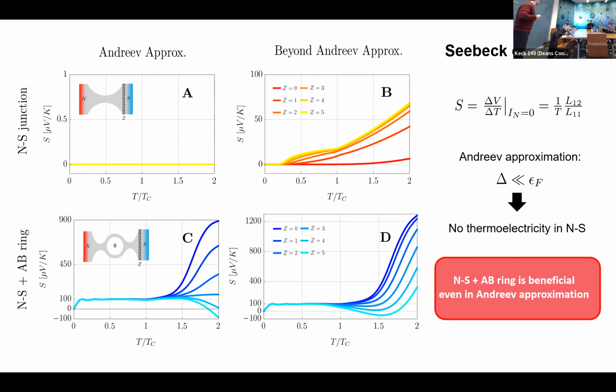So what mechanism breaks the electron-hole symmetry in panel B? Yeah, actually, because within the Andreev approximation, the only process you can obtain is a perfect Andreev reflection, meaning that an electron is just reflected as a hole, and this is it. In the other case, you have just a mixture. So an electron can be partially reflected back as a hole and partly as an electron. This creates interference. Again, you can make the transmission function not an even function of the energy, and indeed you can obtain a finite Seebeck coefficient.